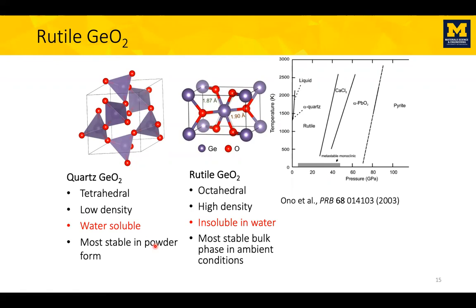Now, I want to start by making a contrast with the quartz phase, right? Silica crystallizes in the quartz phase as well, so they're both stable and they both appear in the phase diagram. The quartz phase is tetrahedral, it has a low density, and the problem is it dissolves in water, so you can't process it with the usual wet etching techniques. But that's what you will get if you purchase the powder from a vendor.